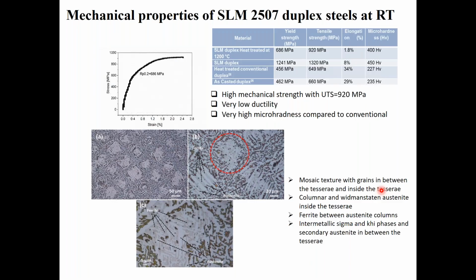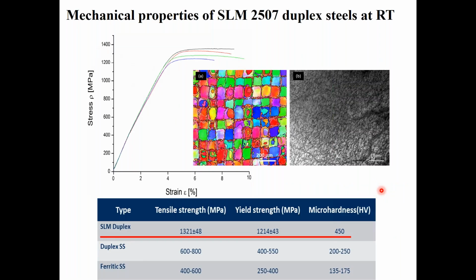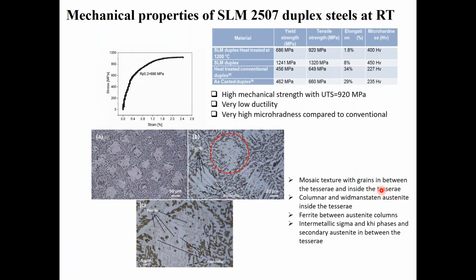And then, since it's only ferritic, we tried heat treatment to get the duplex structure. After the heat treatment, we found that the mechanical strength reduced to 920 and the elongation reduced drastically to only 1.8%. So then we looked at the microstructure and tried to understand why this happens.